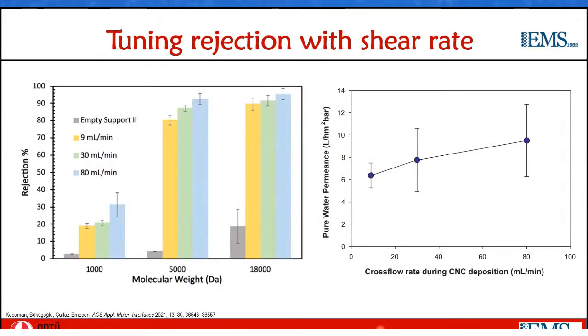And then the next question is how this converts into the membrane performance. Here you see the rejection of 3 different probes we tested. A small one, vitamin B12 of 1.3 kilodaltons of molecular weight, a 5 kilodalton blue dextran, and an 18 kilodalton protein, beta-lactoglobulin. And you see the rejections of the support, as well as the 3 membranes fabricated at 3 different cross flow rates and increasing shear. For the smallest probe with the most aligned membrane, we do see some increase in rejection, but all these rejections are quite small.